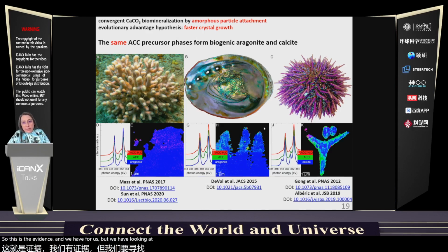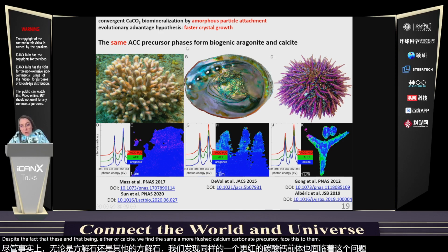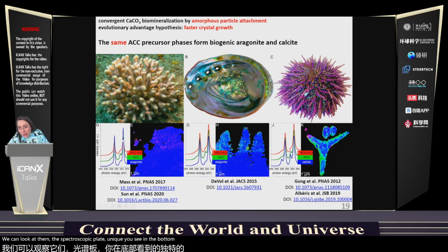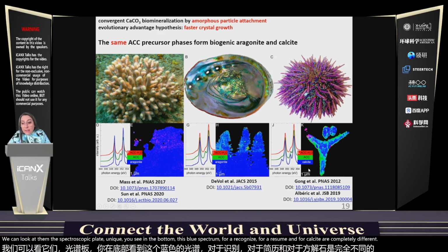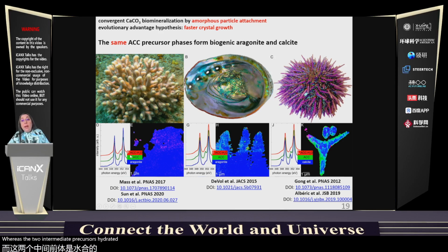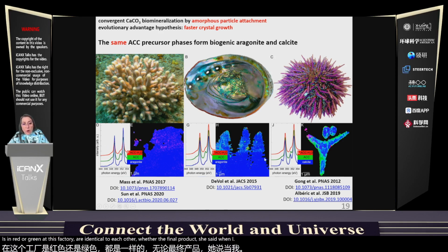We are looking at coral skeletons made of aragonite, at abalone nacre, also made of aragonite, and sea urchin spines or spicules that are made of calcite. Despite the fact that these end up being either aragonite or calcite, we find the same amorphous calcium carbonate precursor phases to them. We can look at them spectroscopically. You see at the bottom this blue spectrum for aragonite, and for calcite are completely different. Whereas the two intermediate precursors, hydrated and anhydrous amorphous calcium carbonate, which I abbreviated ACC here, is in red or green, and these spectra are identical to each other, whether the final product is aragonite or calcite.